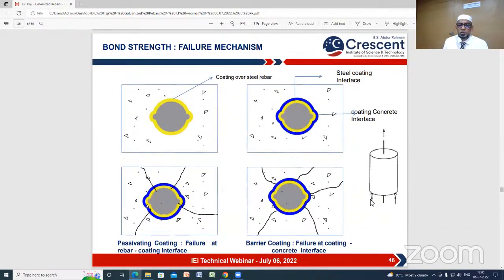This picture shows how the failure mechanism happens when the rebar is pulled out from the concrete, with metallic coating and non-metallic coating. Most of the time with metallic coating, the cracks initiate from the rebar to the concrete. In the case of barrier coating, the concrete breaks from the coating only. That means even after the pull-out test, the coating is not disturbed, which indirectly shows that the adhesion is poor.